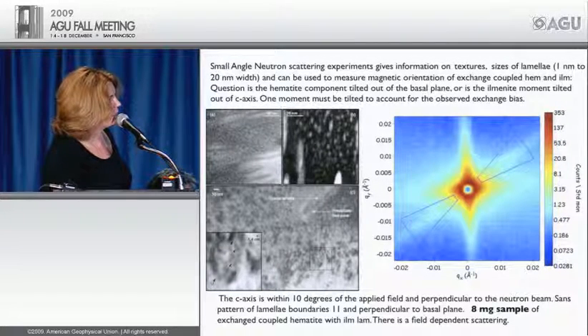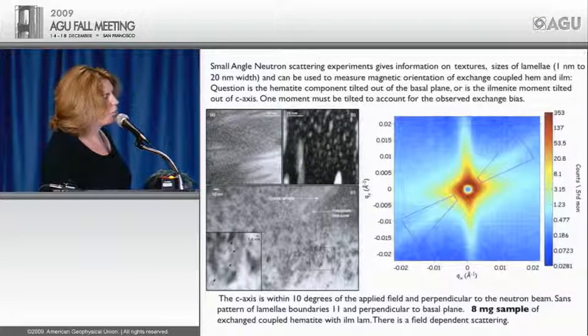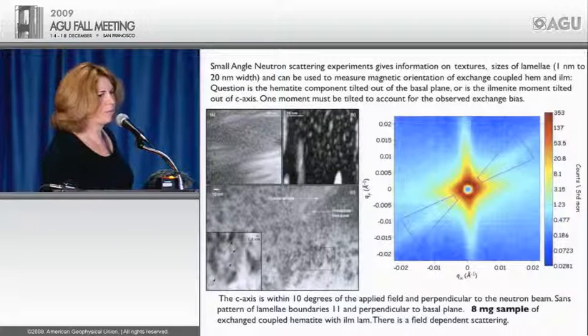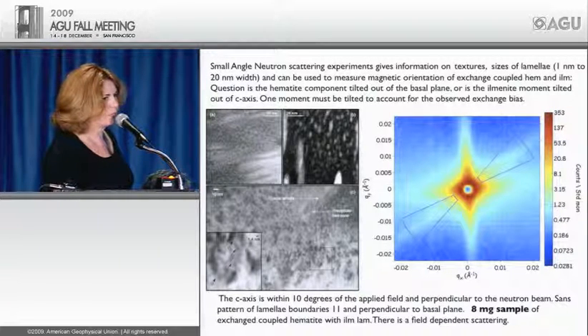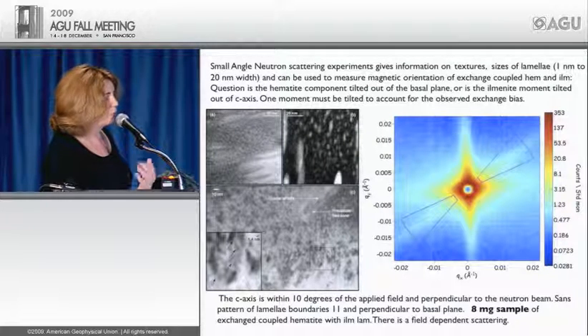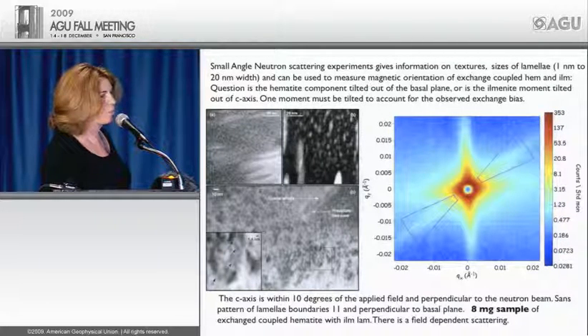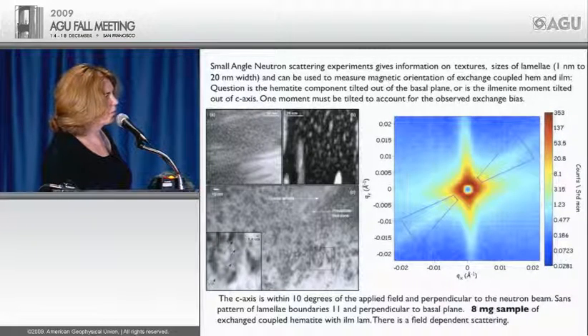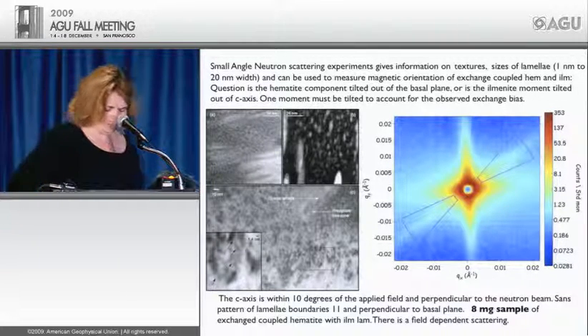And you can see here, these little arrows are showing you these lamellae, and the scale bar there is 1.4 nanometers. The remarkable thing is we were doing this on 8 milligrams. This was something you couldn't have done 10 years ago. So the advances being made in mineral physics, and the amount of material that we can actually measure in these different places, is giving us a tremendous ability to understand the nature of the magnetism of these materials.